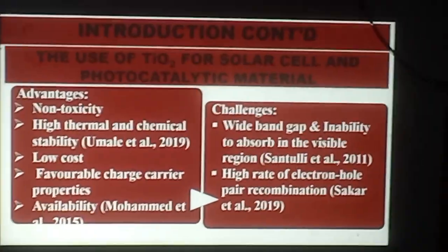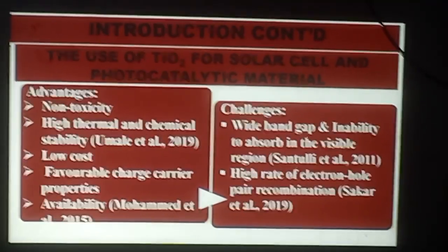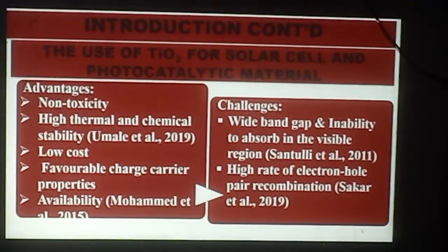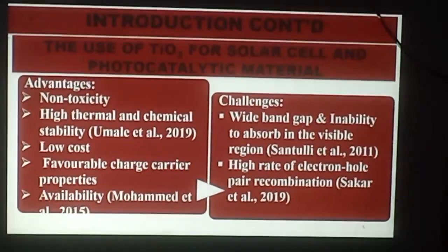The major advantages include the non-toxicity, high thermal and chemical stability, which cause favourable charge carrier properties, and availability of this material. Then we have some challenges, which include the wide band gap of this material, which only enables it to fully absorb in the UV region. Then the high rate of electron-hole recombination.